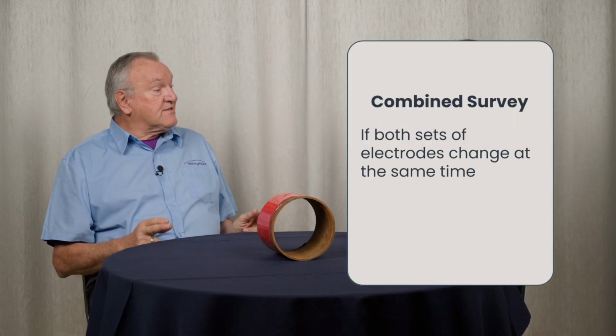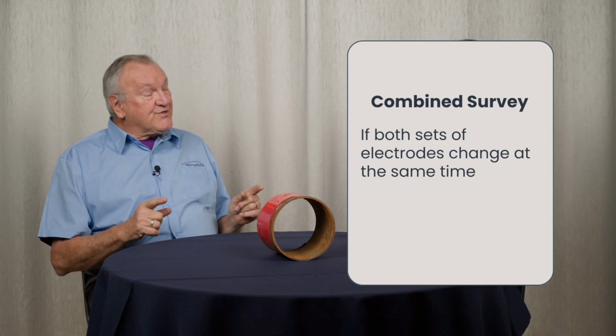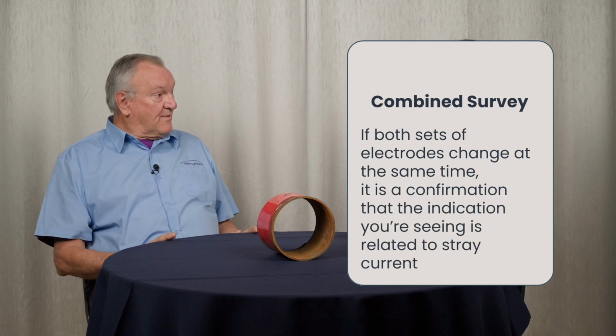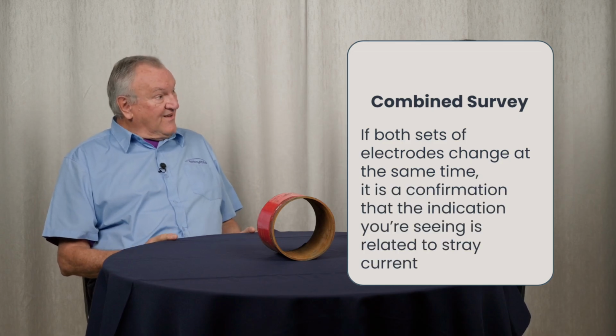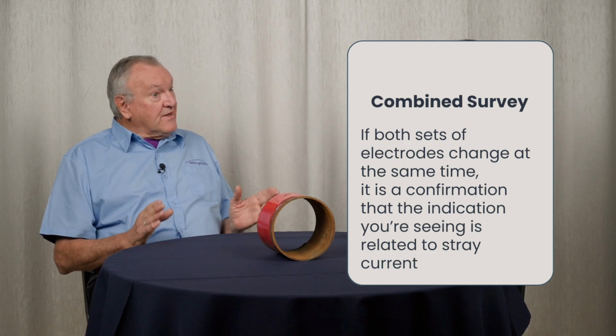When you're doing the combined survey, you've got two sets of electrodes. And if both sets of electrodes are only 10 meters apart, the difference between the stray current effect here and 10 meters away is going to be negligible. So if you find that both sets of electrodes change at the same time, it is a confirmation that the indication that you're seeing is related to stray currents and not to pipeline condition. Oh, interesting. Fantastic. Thank you.